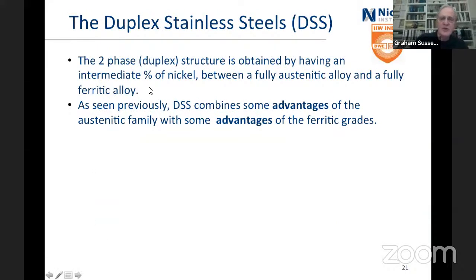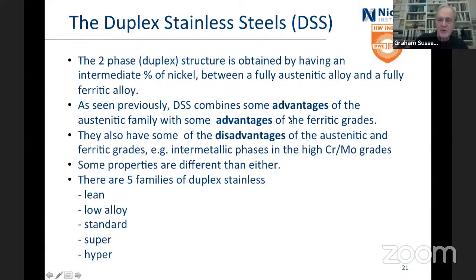It's a two-phase structure, intermediate levels of nickel, somewhere between those. It's got some advantages and some disadvantages, but one of the major ones is these intermetallic phases that occur with the high chromium and high moly grades. So that's the super duplex and the hyper duplex. You can get this with ordinary duplex, but you've got to work hard at putting too much heat into it. Some properties are different from either the ferritic and the austenitic. I'm not going to go into that in detail.